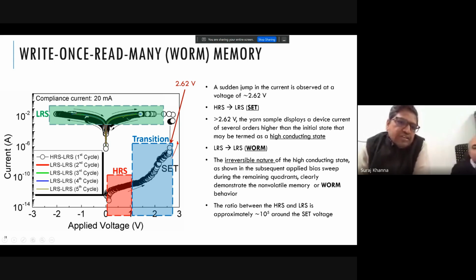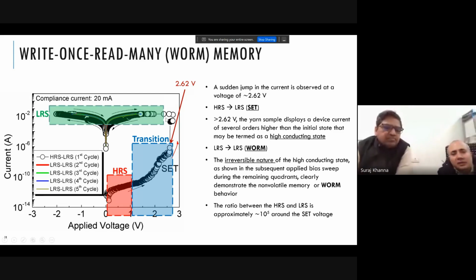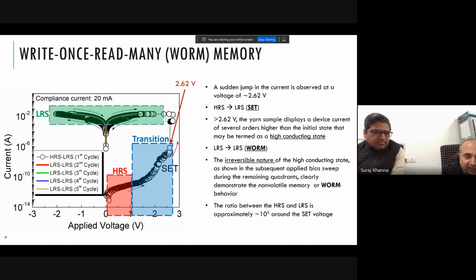This is the ohmic or conductive state once it switches from the high resistive state to the low resistive state. I think this is one of the most important things to take away: this material is not a typical material which can be handled with a standard protocol. If the material gets excited by a higher voltage, it can suddenly turn into a conductive material. If you are working with this material, it can show two different states: highly insulating and highly conductive. Depending on what excitation voltage you use, it can show two different behaviors. I hope that is very clear to everyone.